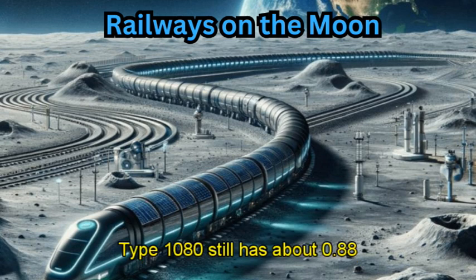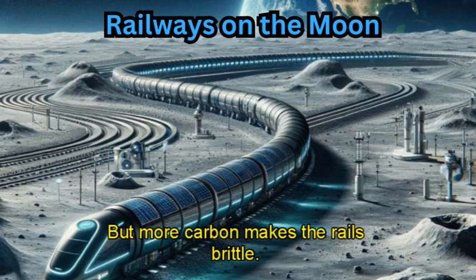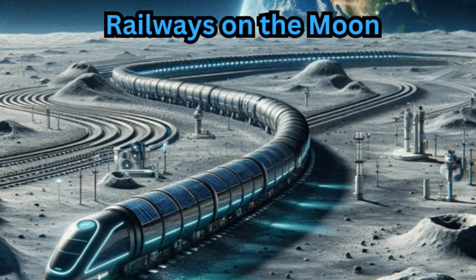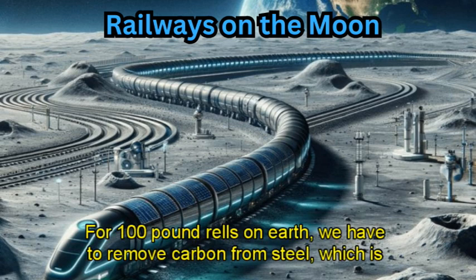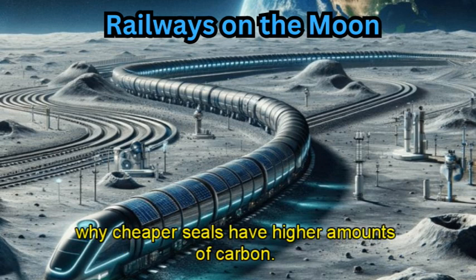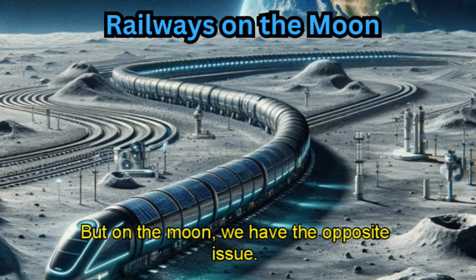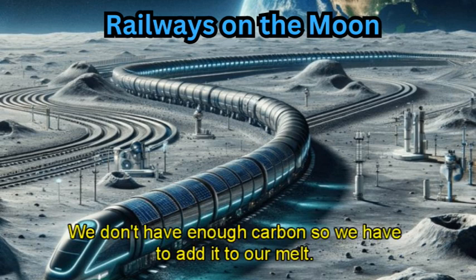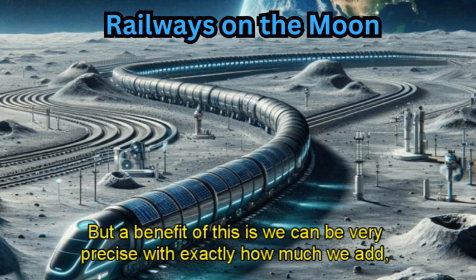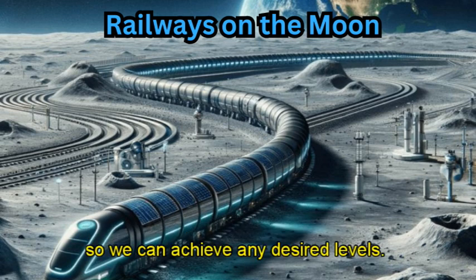Type 1080 steel has about 0.88% carbon, but more carbon makes the rails brittle, and best practices are about 0.5% carbon for 100-pound rails. On Earth, we have to remove carbon from steel, which is why cheaper steels have higher amounts of carbon. But on the moon, we have the opposite issue. We don't have enough carbon, so we have to add it to our melt. But a benefit of this is we can be very precise with exactly how much we add, so we can achieve any desired levels. So let's go with the recommended 0.5% carbon.